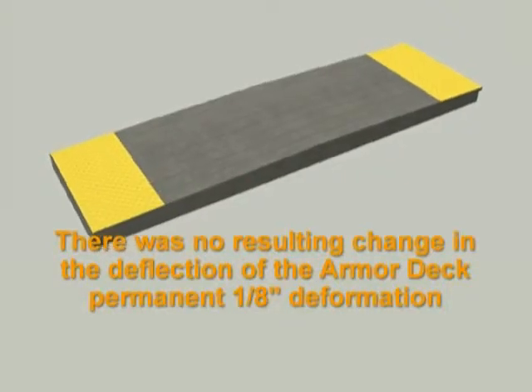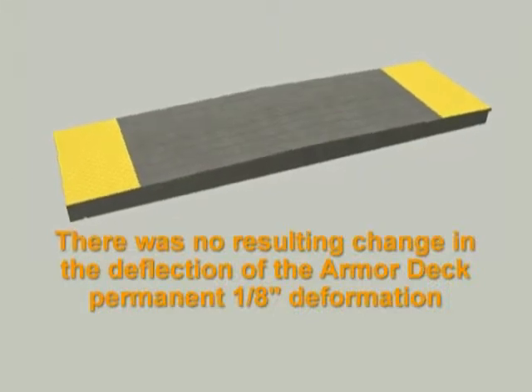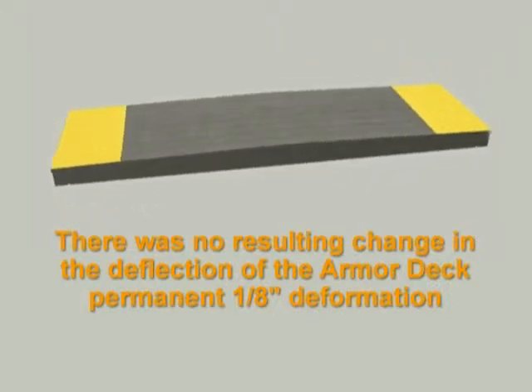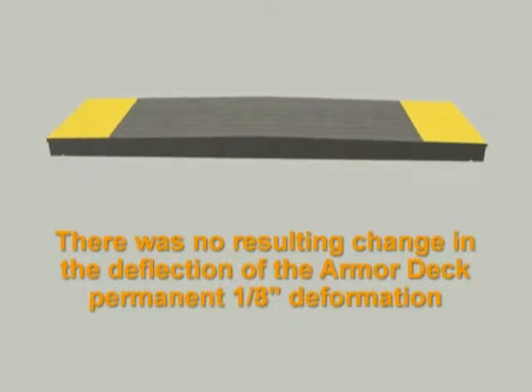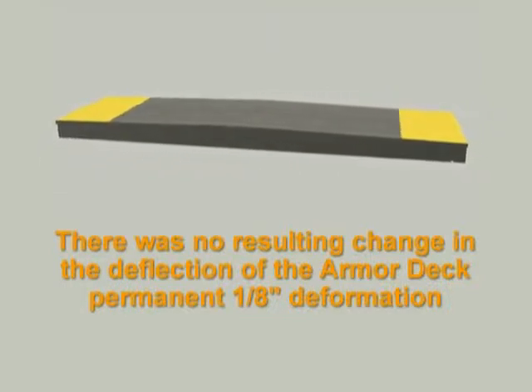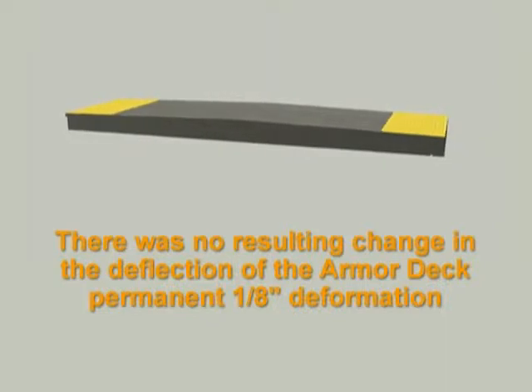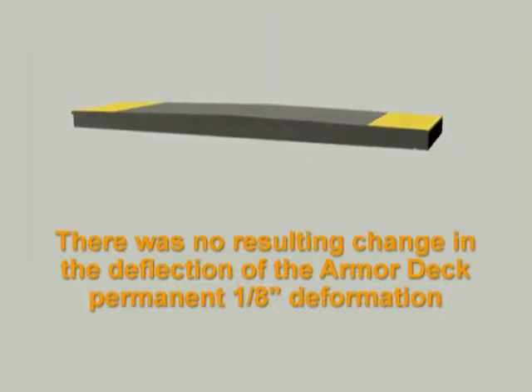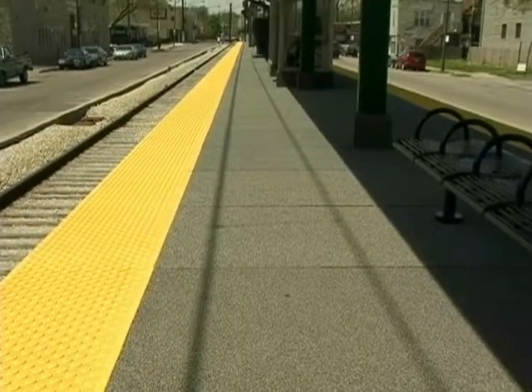It turned out after applying a 600 PSF load, the permanent deformation that had been set into the product was 1/8 of an inch, and that 1/8 of an inch remained after another 24 hours. The design criteria for a load test on such a product would dictate that the permanent deformation not exceed 1/4 of the total deflection, and we achieved a much better recovery than that.